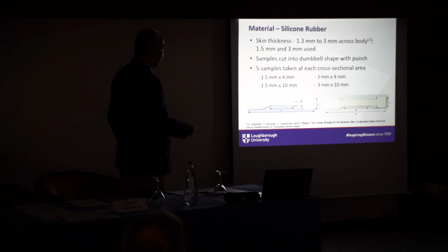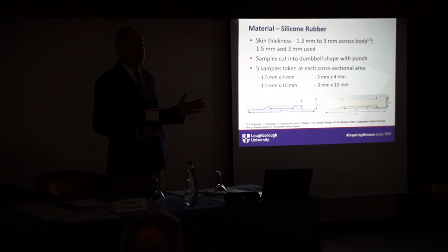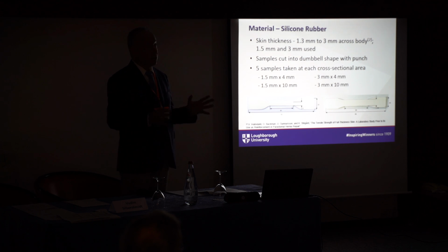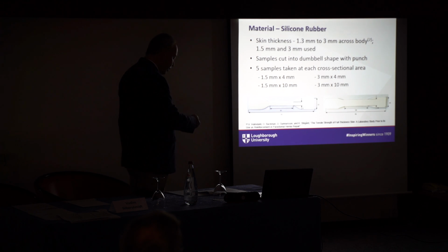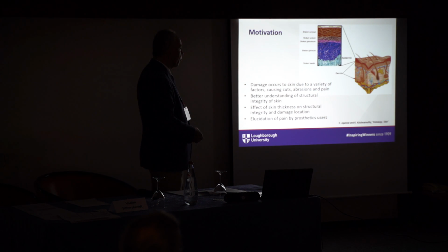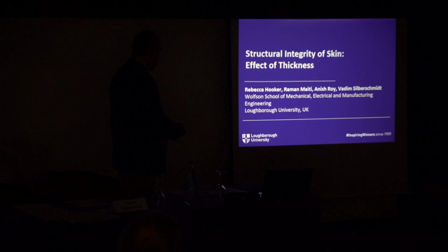The idea about the specimens is that we should clearly try to retain dimensions close to the real ones, and usually the skin thickness, as always, has some vagueness in the definition of what skin specifically is. But I can quickly say that in terms of the skin, we are considering the entire complex layer. This provides a thickness of between 1.3 and 3 millimeters, and that's why we are preparing